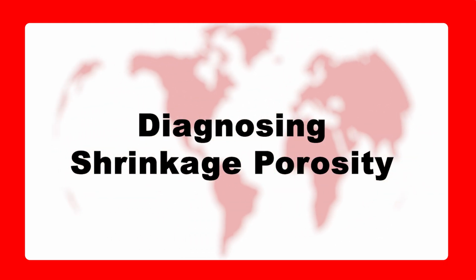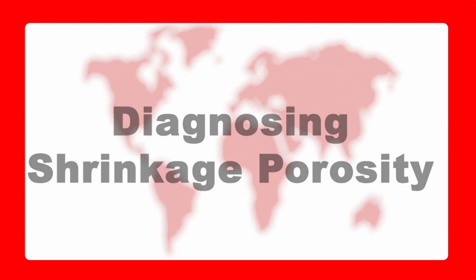Another cause of shrinkage porosity is the placing of castings too close together in the flask. This makes it more difficult for the heat to escape through the investment and doesn't allow for the rapid chilling of the castings. Relatively slow cooling of the castings promotes porosity. Shrinkage is a feeding problem.